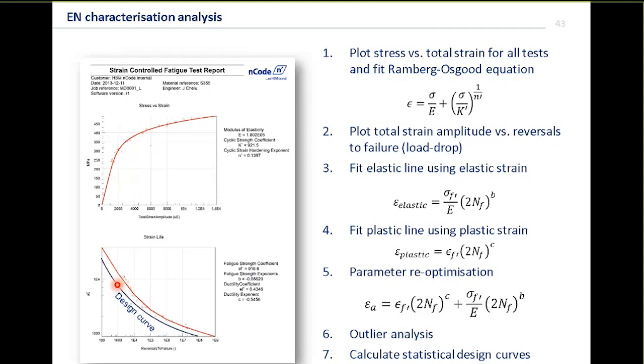And what we're looking at now is characteristics of the material as well. And these characteristics could be fed into your components. So we need to characterize that spread if that's the case. We also have the option in some cases where, if we can't exclude the test because we can't see a reason for it being invalid, but clearly it's biasing the curve, we may take it out of the regression, but we'll include it still in the scatter that we use to derive those design curves. So there are three options with outlier analysis. We can exclude the point, we can include it fully, or we can exclude it from the curve fit, but include it in the scatter that goes into the design curve.